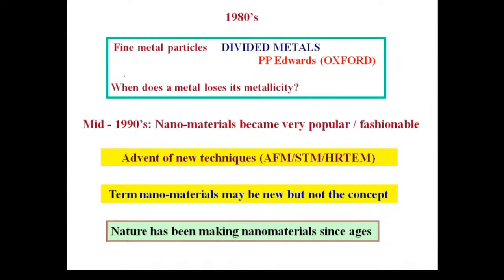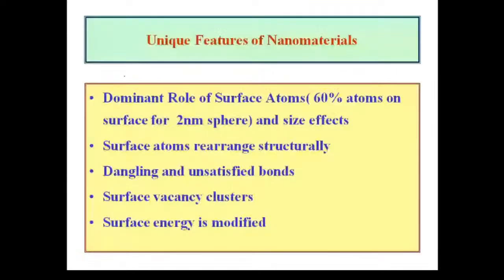When the particle size becomes low, basically a lot of particles come to the surface. In a 2 nanometer sphere, around 60% of atoms will be at the surface. And the surface atom will have more reactivity, and there will be some unsaturated bonds in the surface atom. Dangling bonds will be there, and there will be a lot of vacancies, and the surface energy will definitely be modified. So the total feature of the material will change.